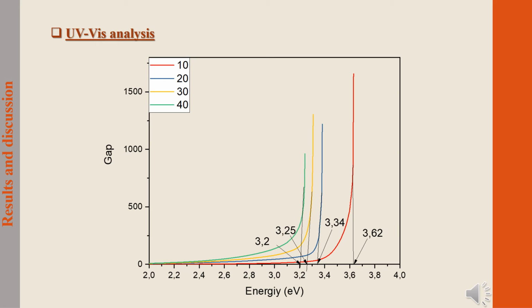To get the gap energy of our material, UV-Vis analysis was performed, showing that the band gap value varies from 3.2 to 3.8 electron volts. Also, we can see that the gap energy of the films decreases with increasing thickness as the number of cycles increases. Obtaining sufficient thermal energy will be necessary to overcome the barrier of activation energy for chemical oxygen absorption and surface interaction. Therefore, in order to optimize the energy consumption of the sensor and to limit the thermal degradation of the detection material while keeping a good response of the sensor under the target gas, we chose to work with the thicker films due to the low gap energy.